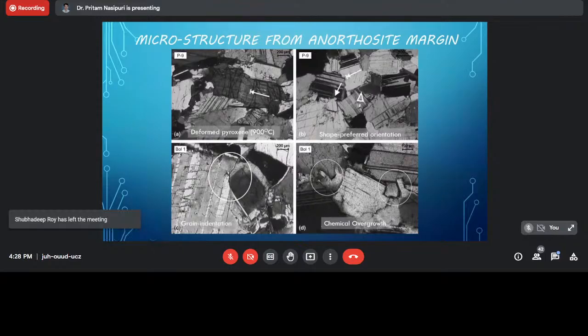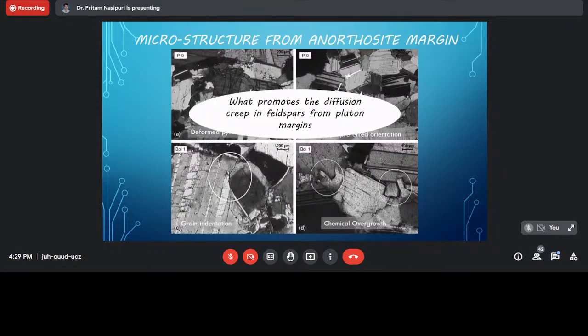That means, wherever in experiments people say, diffusion creep mostly occurs at grain sizes of 1 to 10 micron. Here we provide a natural example that, depending on certain conditions, feldspar may experience diffusion creep where the grain size is more than the experimental size. Now the puzzle: what promotes diffusion creep in the feldspar from the pluton margin? Usually these grains are large, and the temperature is 900 degrees, this is high temperature. So what promotes this deformation?